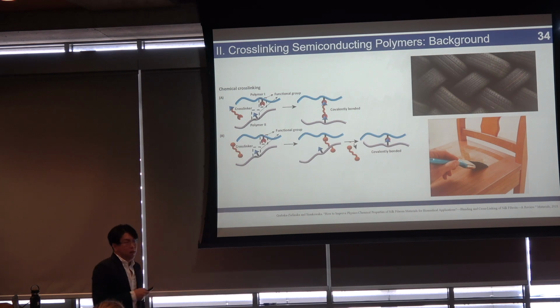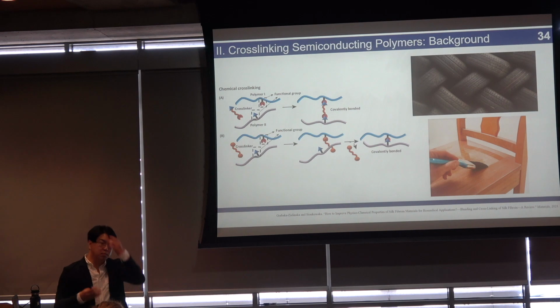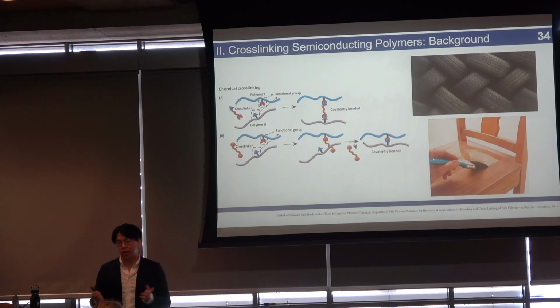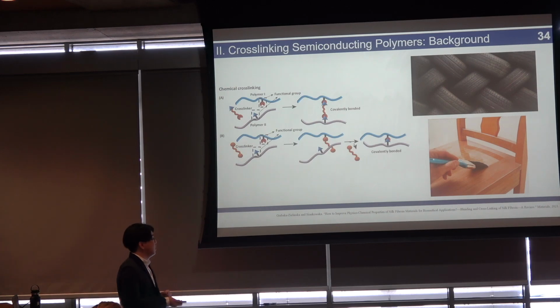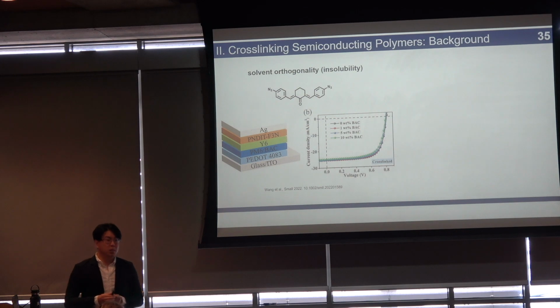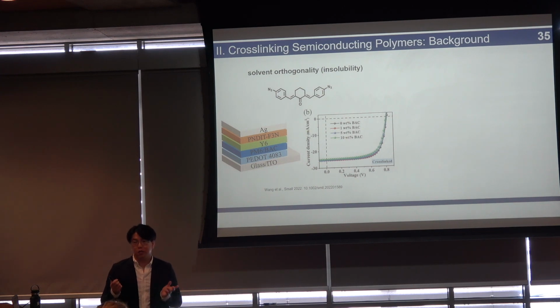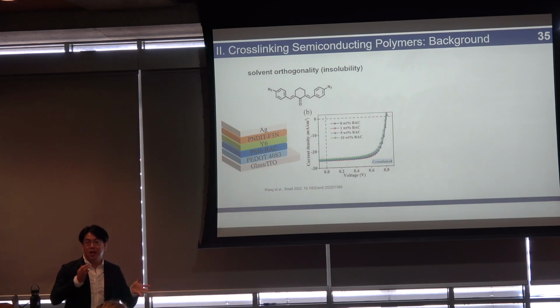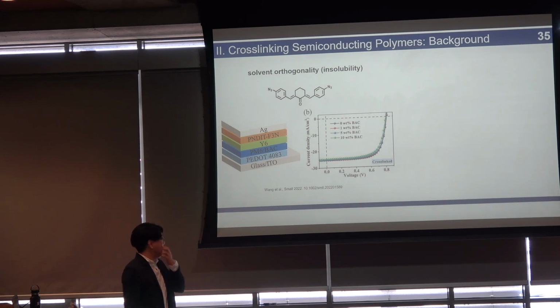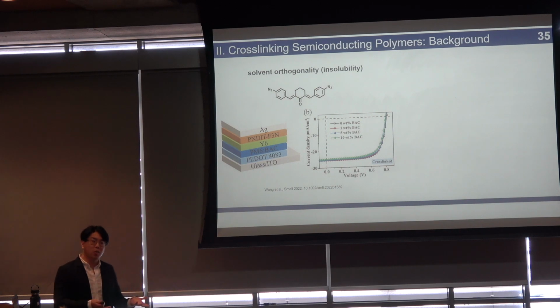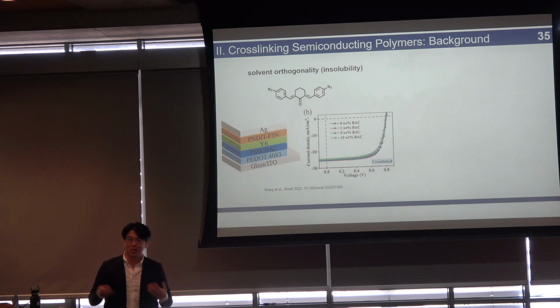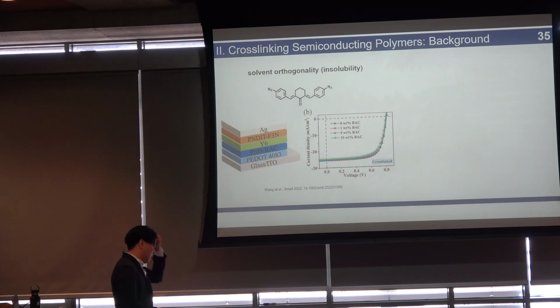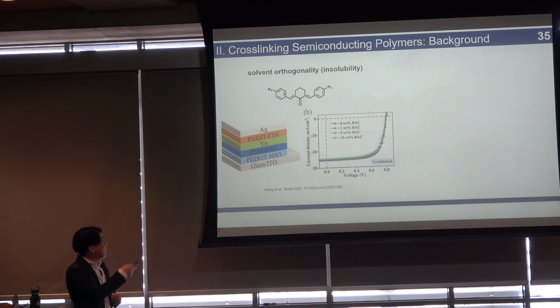And the way these work is the polymer chains in these materials are cross-linked. So there's covalent bonds that are formed between these long polymer chains. And for semiconducting polymers, this has been explored for a couple different reasons. First and foremost, this enables solvent orthogonality. What we mean by this is that cross-linking your film makes it insoluble. The morphology is frozen. And normally for a solar cell, you have to mix a p-type and an n-type material together. So when you have an insoluble layer, you could actually spin things layer by layer, because otherwise the top layer would dissolve the bottom layer because they use the same type of solvent. In this case, because the bottom layer is insoluble, you can deposit things step by step.